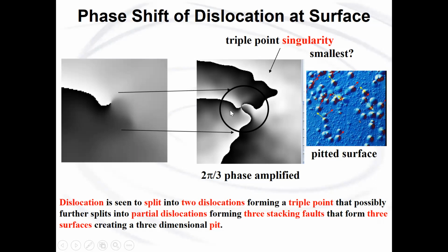And so in this case, what we're doing is imaging the dislocation from within the crystal to the surface, whereas normally we see these dislocations on the surface forming etch pits, but we can't see any detail in these. So the model that I'm going to present is a dislocation that's splitting into 2 dislocations to form a triple point. And then those 3 dislocations can further split into partial dislocations, forming 3 stacking faults, which form 3 surfaces to create a 3-dimensional pit.